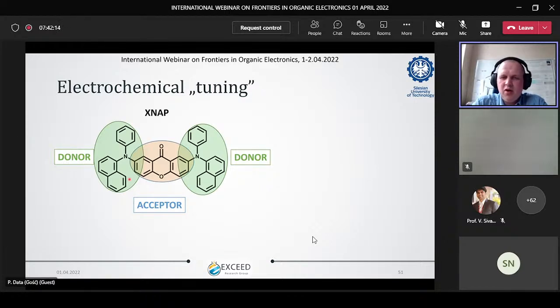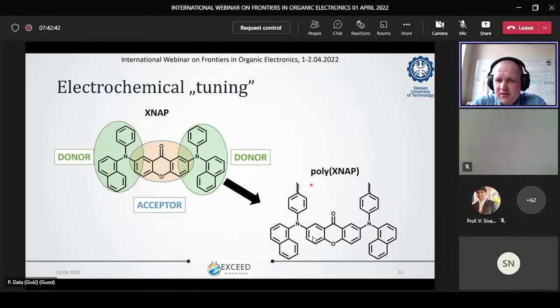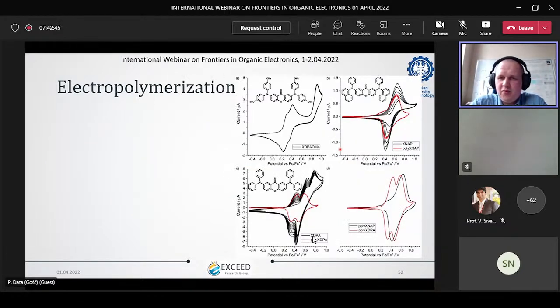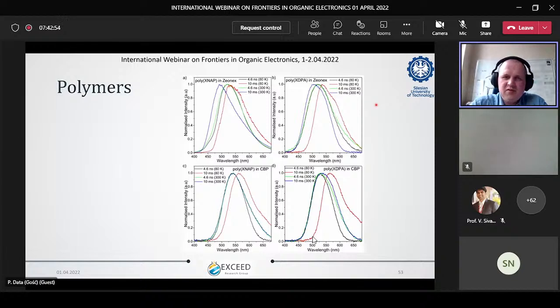Acceptor should remain. So everything which is associated with acceptor, like in our case or in most of the cases, phosphorescence process, phosphorescence emission, should remain, and our charge transfer state, which is associated with donor, should drop because we'll have higher conjugation and you should have higher emission wavelength, so lower energy. Like in this case where we'll get our polymer. Here is a presentation of the processes where we are forming our polymer, which is increasing, but I will skip that.